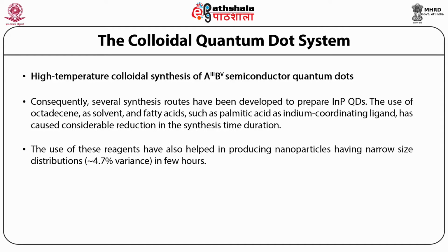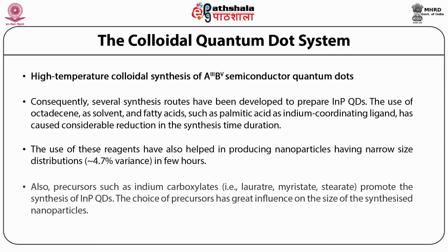The use of these reagents has also helped in producing nanoparticles having a size distribution of about 4.7% variance in a few hours. Also, precursors such as indium carboxylates promote the synthesis of indium phosphide quantum dots. The choice of precursor has great influence on the size of the synthesized nanoparticles.